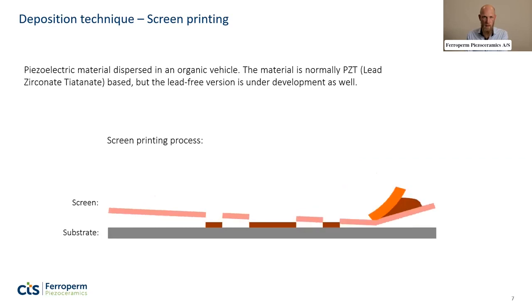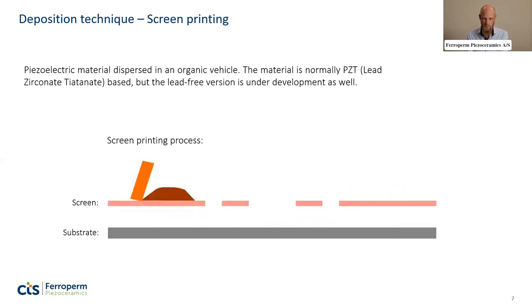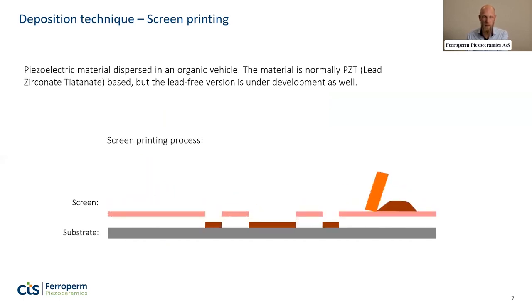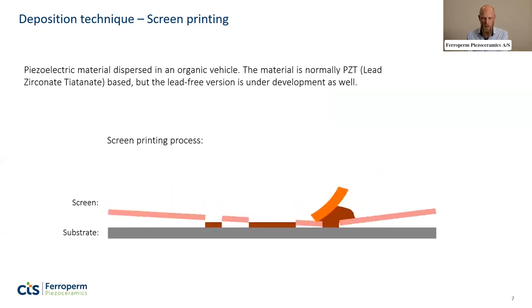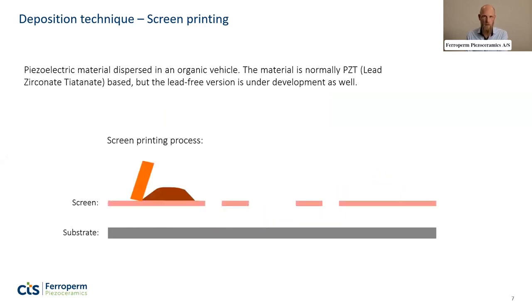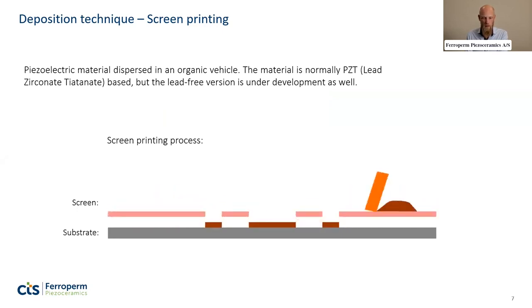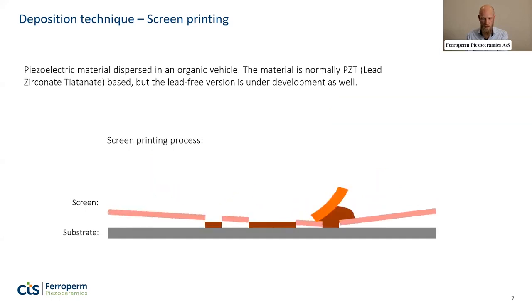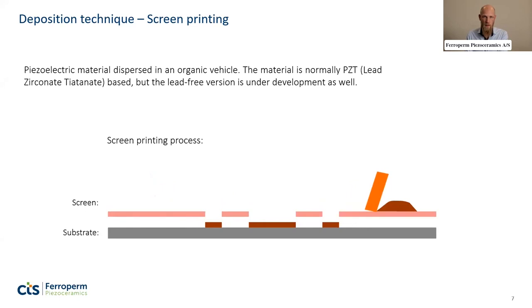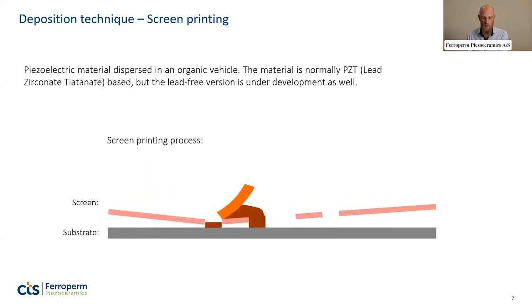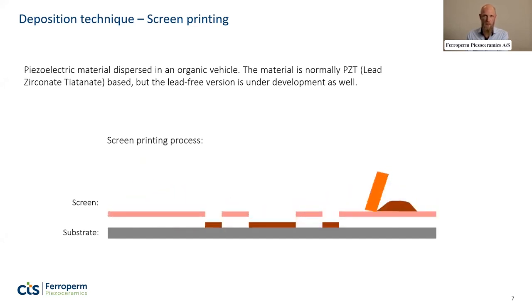Okay, so what is it exactly that we're talking about in the case of thick film? Basically, you have to imagine a ceramic film deposited on a substrate. And the way to do that is to take the powder, this piezoceramic powder, and mill it into a reasonable particle size, and then disperse that into an organic vehicle. So you get a paste, and the paste can then be printed using conventional screen printing, which is demonstrated here in the little animation. And then you can basically utilize the advantages of screen printing technology to make a thick film, a ceramic thick film on a substrate. And that includes scalability, volume, low cost, and of course the resolution that screen printing enables.